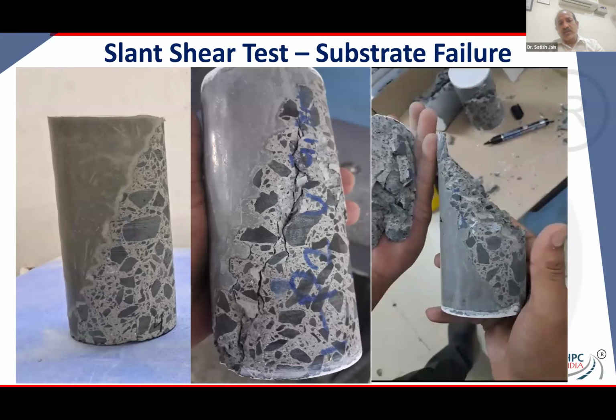And these are core samples. The concrete part is the core samples that were actually taken from the bridge deck, which were roughened, and UHPC was poured on top of it. Then, of course, after all the strength gain, the slant shear test was done. And you can see the failure. The failure is in the concrete. It is not in the bond or the UHPC.